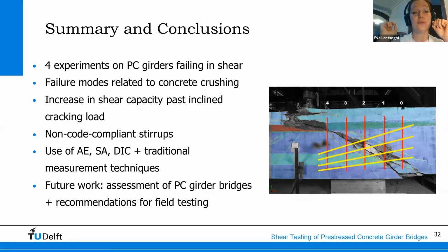All failure modes were related to concrete crushing, either crushing as in shear compression, so losing the compressive capacity in the strut, or local crushing in the compression zone, or crushing in the compression field. We saw that we could increase the shear capacity past the inclined cracking load, which indicates that the non-code compliant stirrups can carry load and function as regular stirrups.